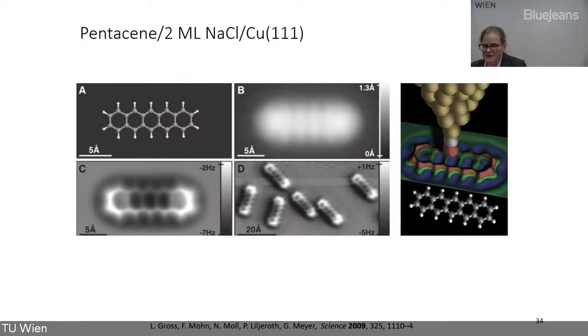Now, key is not only this qPlus sensor I mentioned before, but also what Leo Gross and colleagues started doing: at the very end of the STM tip, they mounted a CO molecule. So they functionalized it with one single CO molecule, and then you can take these really fantastic images.